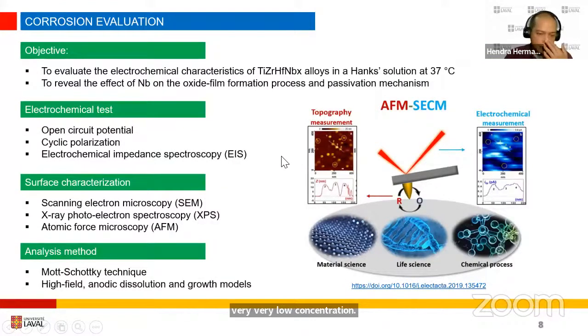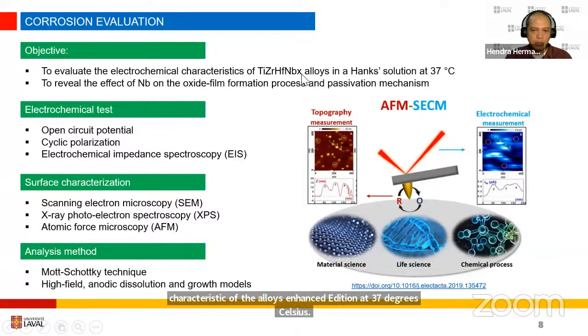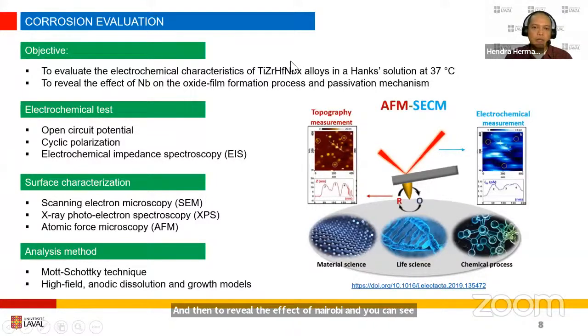And then since its corrosion characteristic is not known quite well, especially in simulated body fluid, we do some corrosion evaluation of this alloy with the objective to evaluate the electrochemical characteristic of the alloys in Hank's solution at 37 degrees Celsius, and to reveal the effect of niobium. You can see it's NbX, so we vary the content of niobium, to reveal the effect of niobium on the oxide film formation process and passivation mechanism.